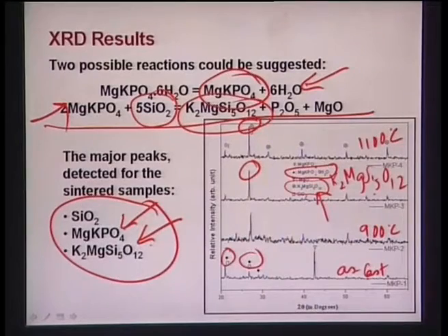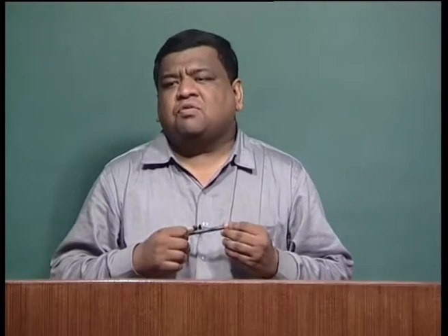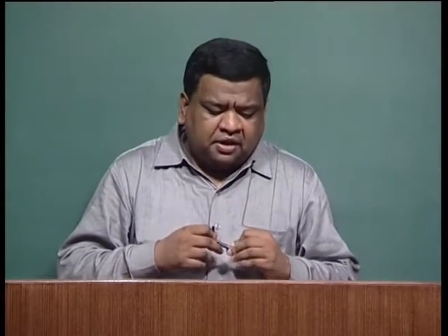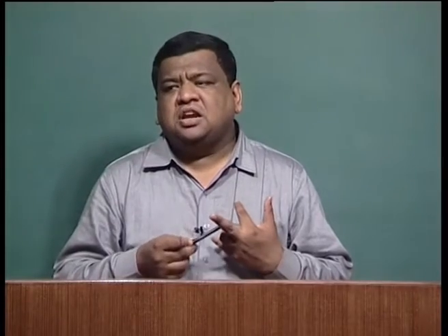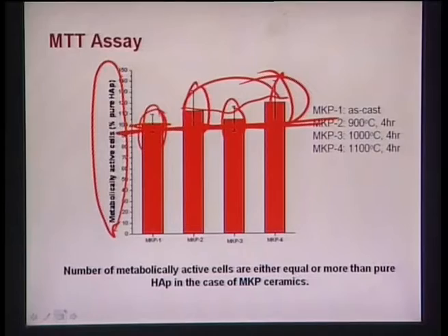Now, the phosphate phase is already well known to have good biocompatibility, like Ca10(PO4)6(OH)2, because hydroxyapatite has good biocompatibility. So we were a little bit worried, because this has an additional silicate phase, K2MgSi5O12, whether the presence of the additional silicate phase will degrade the MTT values or the cytocompatibility property. But our results show that the additional presence of this silicate in addition to phosphate gives you comparable cytocompatibility, comparable MTT values to that of the pure hydroxyapatite.